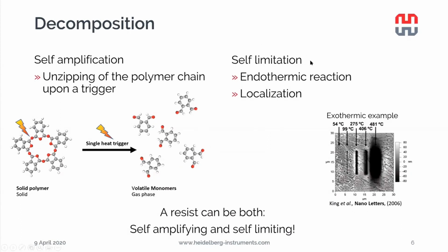The self-limitation basically is the heat output of the reaction. If you have an endothermic reaction of this breaking of the bonds, then there is no further heat source induced to the system, and the whole unzipping reaction is very localized to the tip, heat influx zone of the tip.